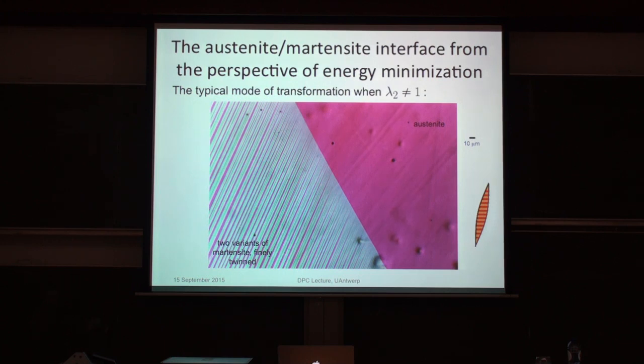So I won't tell you the theory. There is a quantitative theory, but the physical understanding is the following. The first guess would be you take austenite, and over here you put a single variant of the martensite. That's, in fact, one of these bands. So you fill the region, instead of this structure, with one of those bands. And you would find that in order to fit that together with the austenite through a transition layer, there would be an enormous amount of energy in that transition layer, an enormous amount of stress. So somehow the phases don't fit together.